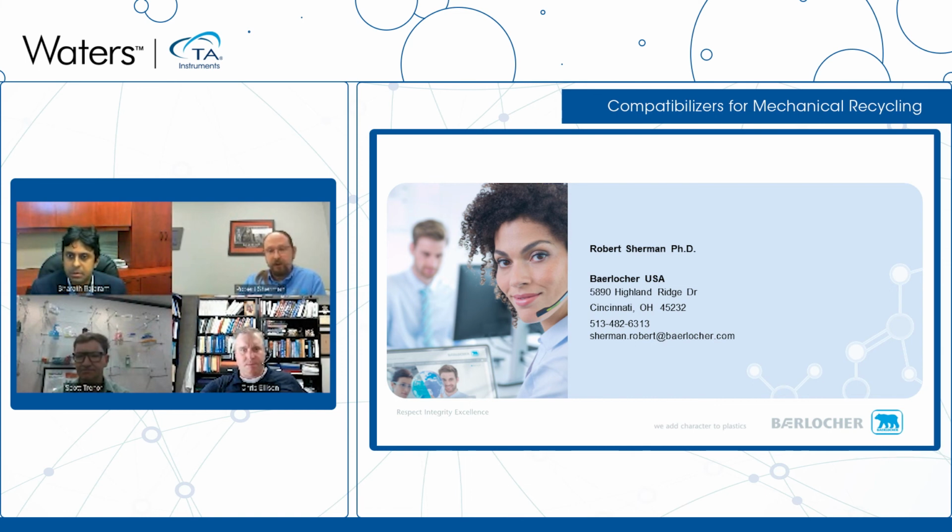Yep, and I definitely agree as well. It's going to be very difficult. Ideally, you don't mix them together in the first place, like whenever you're making your structure. But then again, a mixture of polyethylenes isn't that bad. When you start mixing polypropylene in with polyethylene, now you get your phase separation and immiscibility, and mechanicals and rheology just go crazy on you. So to me, blending polyethylenes isn't so bad. It's more when you get into the other, specifically polypropylene mixed with any of the polyethylenes, that you get problems. Right. I think that's an ongoing challenge in sourcing these types of recycled materials from the waste streams that are available today.